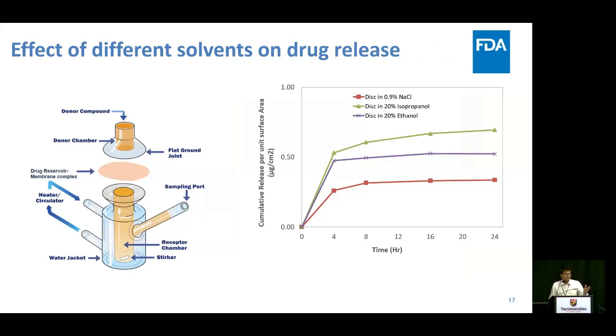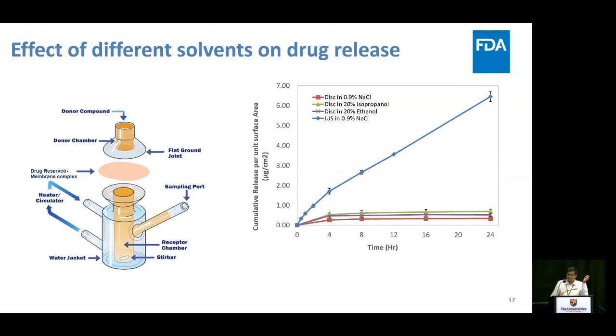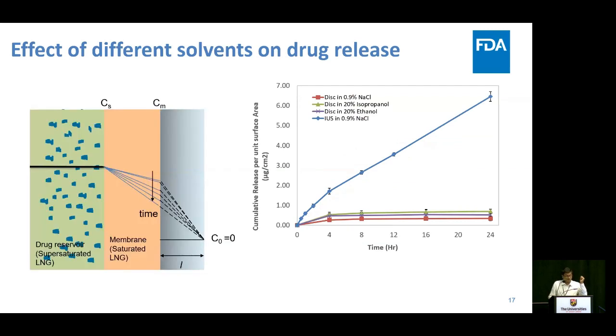Now, the prediction of HSP was also experimentally proved here. Among the three solvents we used, isopropanol showed the fastest release, followed by ethanol and normal saline. That was the prediction from HSP as well. But when we compare this release to the release from the IUS device itself, the amount of drug coming out seems really smaller compared to the device itself. Why so? This goes back to our initial hypothesis and the thickness of the membrane itself. The thickness is way higher compared to the device itself, so it takes more time for the drug to cross this distance. So membrane thickness also affects drug release.